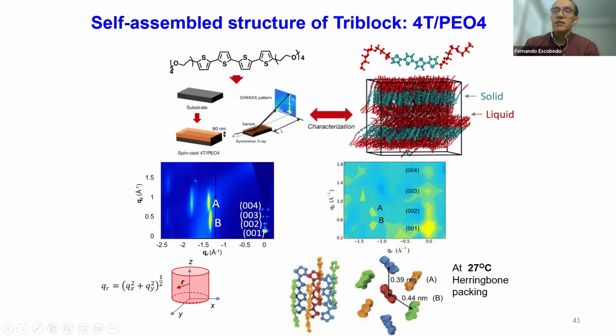So in the figure up here, the thiophene regions are in blue, and the PEO regions are in red. What that demonstrates is that these thiophenes are packing in the same way that thiophene will pack in its crystalline state. So that's telling us that you have something like a solid when you come to the packing of the thiophene cores, while you have something that's much more amorphous, kind of liquid-like, when it comes to the structure of the PEO chains. Now this seems strange, because now that you have this structure, is this a solid?